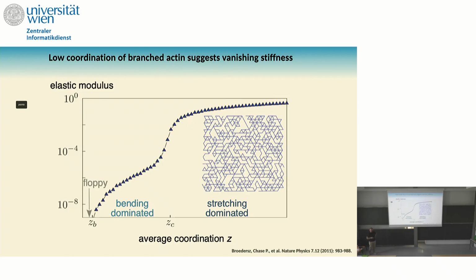Now, if you take your tree-like structure for the branched actin, and you count how many constraints you have, what is the average coordination number that you get for this structure, you realize that your branched actin falls exactly at that point, which means within this framework, I expect that if I apply a deformation to this branched structure, I expect it to be floppy. So from where is this nonlinear elastic behavior coming?